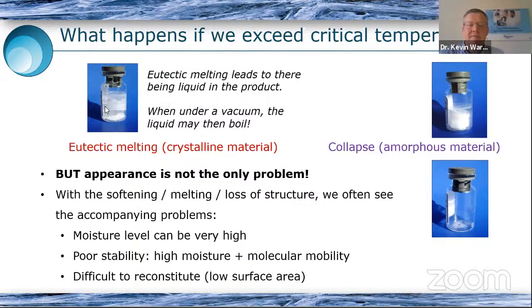And so here on the top left, this vial is showing a solution which we know is a crystallizing solution, but it has a very low eutectic temperature. And so when you go above that temperature in freeze drying, the ice may remain solid, but between the ice crystals, we will have a eutectic liquid. Now, what does the liquid do under vacuum? Well, it could then start to boil, which is what's happened in this case. And so you can see that the product has effectively erupted up the side of the container. It's almost managed to escape, in fact, through the stopper, which would have been open during the sublimation. So this is, of course, a risk.